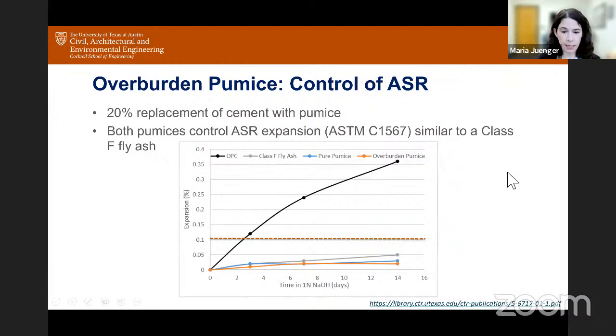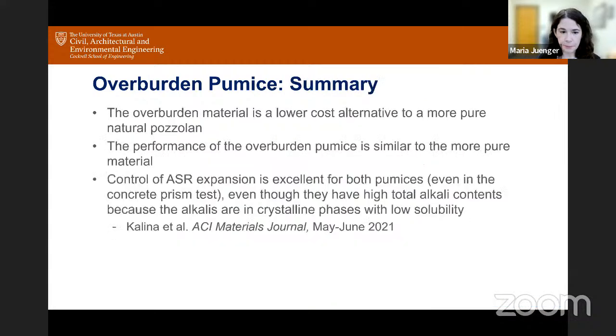Another thing we often look at is how these materials control expansion due to alkali-silica reactions. So how do they impact durability? In this particular test, the black is the control, the aggregate with just straight Portland cement, and all of the pure pumice, the overburden pumice, and the class F fly ash all reduce expansion below the threshold in that particular 14-day rapid test method, the accelerated mortar bar test. So they all behave similarly in terms of durability.